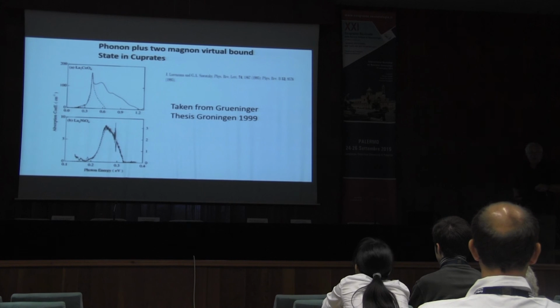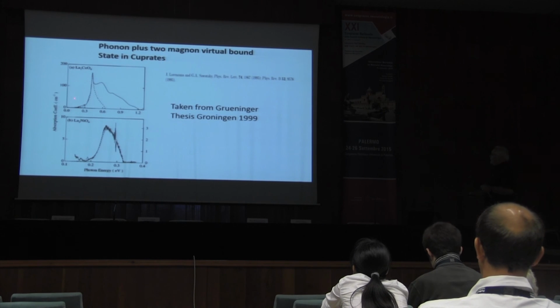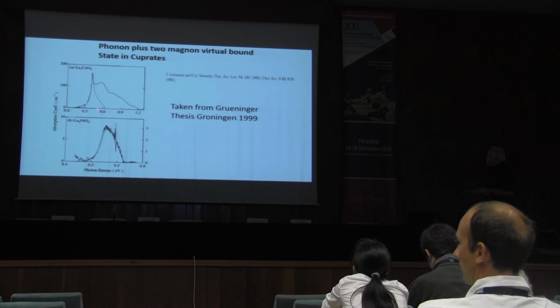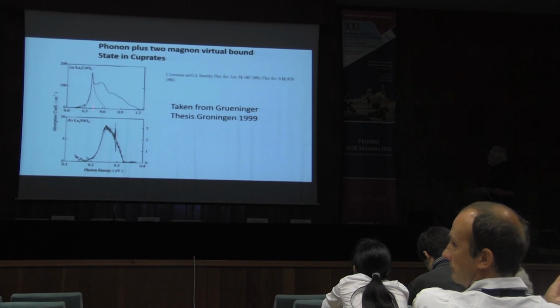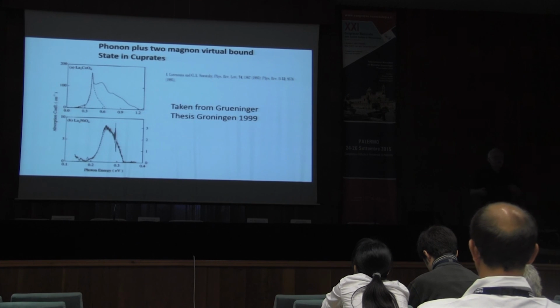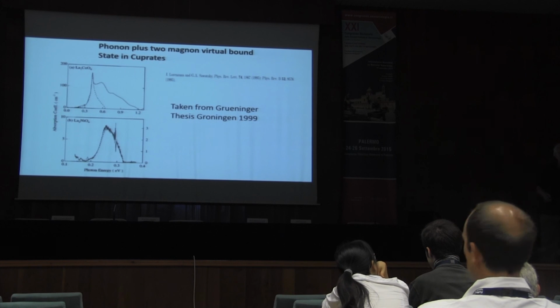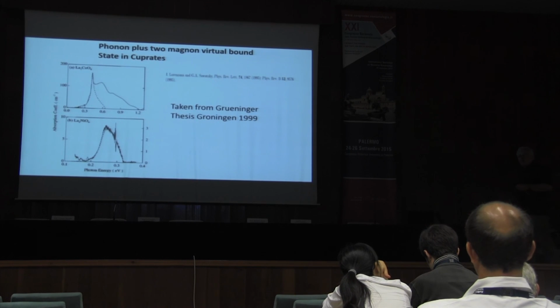And you can actually see these phonons plus 2 magnons. In the undoped material, you have an infrared absorption at about 0.5 eV, which is very, very sharp, and actually corresponds beautifully to a theory of a phonon plus 2 magnon at particular places in the Brillouin zone, most of them at the zone boundaries. You need 2 magnons because in optics your net spin change has to be 0, and you have to have a phonon to compensate for the momentum, because your total momentum has to be 0 in optics also.